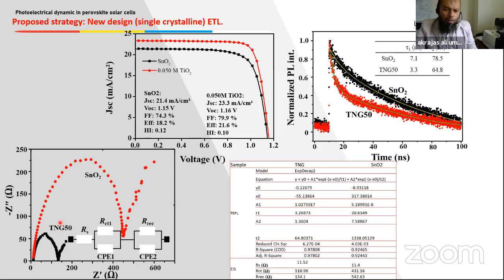This phenomenon is also further supported by the electrochemical impedance spectroscopy result, which shows that the interfacial charge transfer resistance in the nanograss based device is much lower compared to the SnO2 based device. We fit this result with this equivalent circuit so that we can get the interfacial charge transfer and also recombination resistance. As we can see in this table, the recombination resistance in TiO2, I mean nanograss, is much lower than SnO2, which means that recombination in TiO2 is also high,